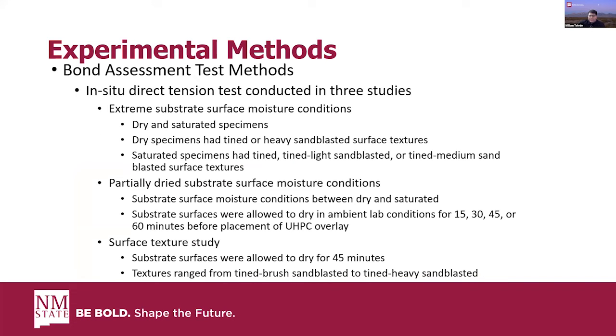Okay, so this research is broken up into 3 studies. The first being the extreme substrate surface moisture condition study, where we investigated dry and saturated specimens. Again, the dry was dried for 2 hours or 120 minutes, and saturated specimens were maintained saturated up until application of the UHPC overlay. So they had visible moisture and freestanding moisture. Okay, so the dry specimens had a tined or heavy sandblasted texture, and the saturated specimens had a tined light sandblasted or a tined medium sandblasted surface texture.